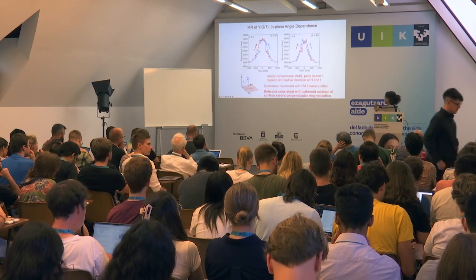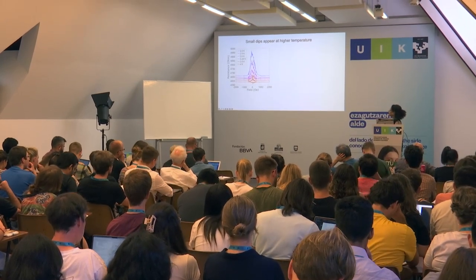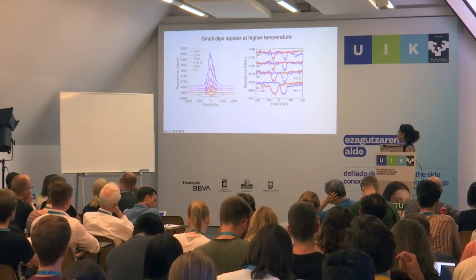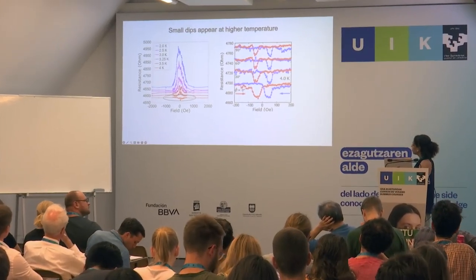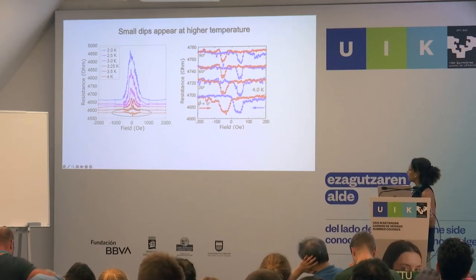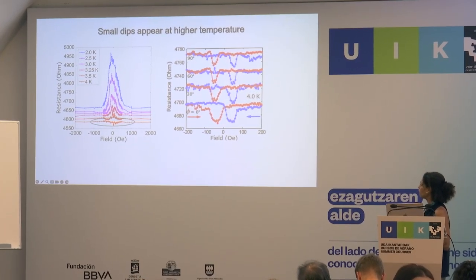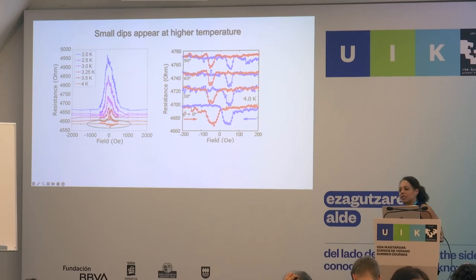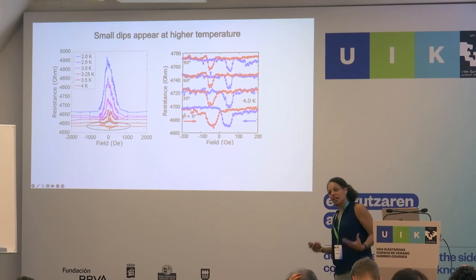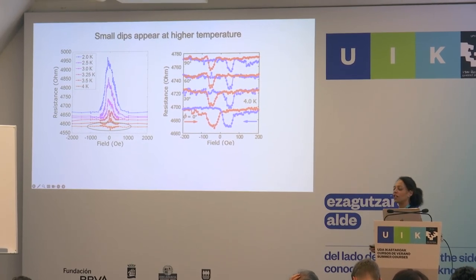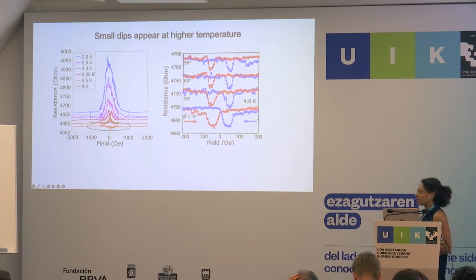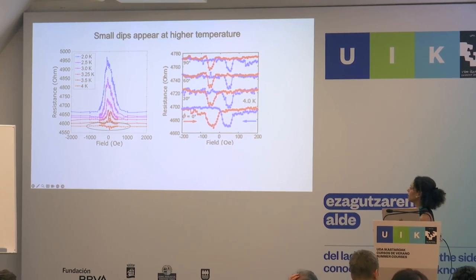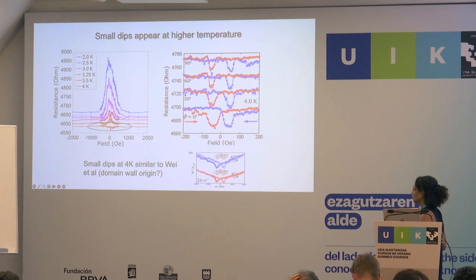So at least this behavior is consistent with the rotation of the surface state's magnetization. We note that the small dips that appear here are consistent with what was seen before on these MBE multilayers that were associated with domains. They look very similar and have very similar characteristics. So it's possible that these states appear with some level of proximity coupling, but with a very strong level of proximity magnetization, you get much larger peaks appearing at lower temperatures.